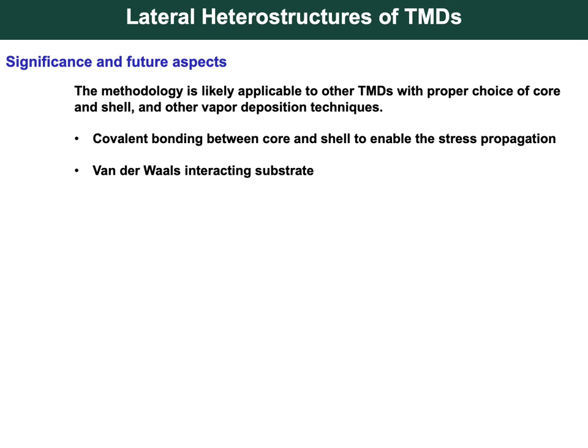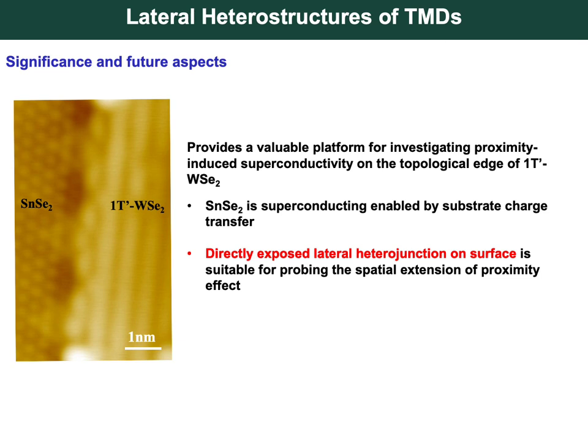In summary, this methodology is likely applicable to other TMDs with proper choice of core and shell, and to other deposition techniques. The two key components are: first, a covalent-bonded core-shell junction to enable stress propagation, and second, a van der Waals interacting substrate to give the shell lattices freedom to rearrange during the merging process. Furthermore, this SnSe2 and T-prime WSe2 heterostructure provides a valuable platform for investigating proximity-induced superconductivity on the topological edge of T-prime WSe2, since SnSe2 becomes superconducting at low temperature via charge transfer with the substrate. The direct lateral heterostructure between superconducting SnSe2 and topological T-prime WSe2 is suitable for probing the spatial extension of this proximity effect. Thank you for your attention.